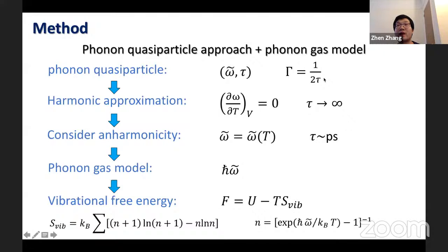However, when we consider anharmonicity, omega becomes temperature dependent, and the phonon lifetime is finite and usually in the magnitude of picosecond. By incorporating the temperature-dependent phonon frequency into the phonon gas model, we can easily compute the vibrational entropy and the vibrational free energy, including anharmonicity.